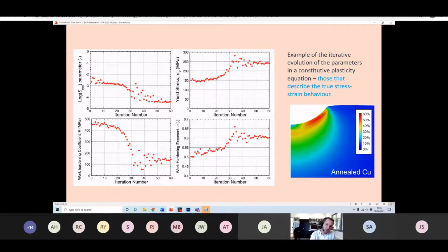On the lower right-hand side, I'm simply showing an equivalent plastic strain field from an indentation finite element simulation, showing that peak plastic strains of around 60% exist within the material when you do these type of tests, and that is a complex three-dimensional strain field, and that complexity is important because that complexity cannot be captured in analytical methods for inferring stress strain curves from indentation test data. Despite people and organizations and institutes trying to do this, this level of complexity can only actually be captured by employing tools like FEA. It's really important as well.